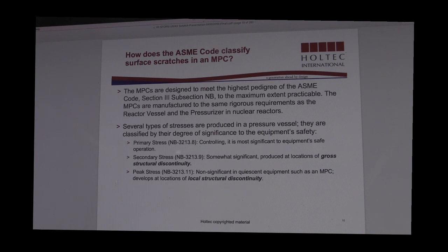The next tier of stress category is secondary stress. These are somewhat, I guess, less significant, if you will, as compared to primary stresses. And these tend to be associated with gross structural discontinuities, which I mentioned earlier. An example of secondary stresses would be the local stresses in the vicinity of the shell to base plate joint. That gross structural discontinuity would produce secondary stresses in that area.